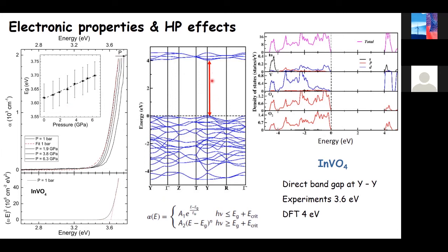Calculations confirmed that the band gap is high. Indeed, DFT predicts 4 eV. And you can see here that the top of the valence band is mainly dominated by p orbitals of oxygens, with a contribution of orbitals from indium, but the bottom of the conduction band is dominated mainly by 3d vanadium atoms. This will explain why we have this. If we have an increase of the repulsion between bonding and anti-bonding states of the vanadates with pressure, because the bond distance is decreased, you expect an increase of the band gap, as we have seen in our experiments.